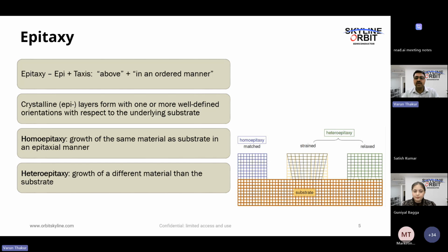So in the figure I have shown, if the lattice is completely matched, then it is homoepitaxy. And in heteroepitaxy, the lattice may not be completely matched, and so we get a little bit of strain, which we use different methods to turn into a relaxed layer. As you can see here at the bottom, maybe I'll use a laser pointer, some of the atoms adjust to make a relaxed layer, right? So going ahead,